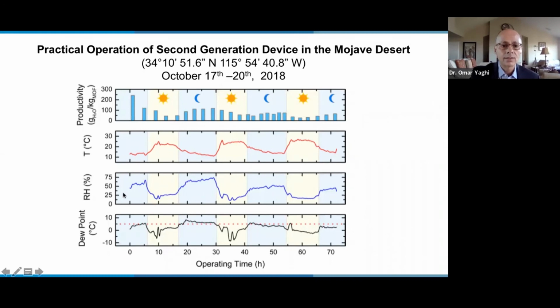And you can see here, if you monitor the relative humidity, I would like you to focus on this panel. You see that during the night, the humidity is high. During the day, the humidity is extremely low. It goes down to almost 10% relative humidity. And whether it's during the day or during the night, you can see that we are harvesting water. And that's the power of this MOF, that it works at ambient temperatures, but it also works at very low humidities, and it can operate for 24 hours.